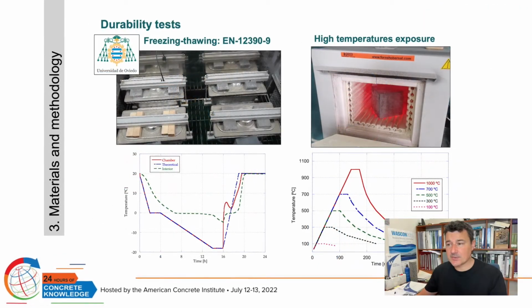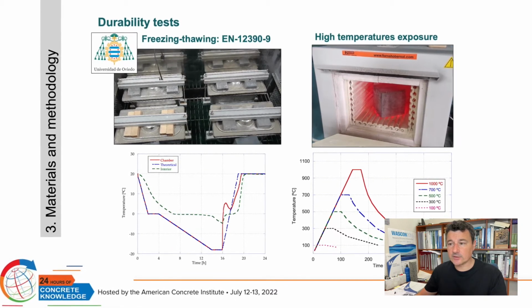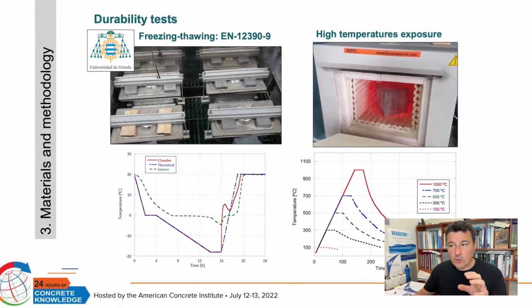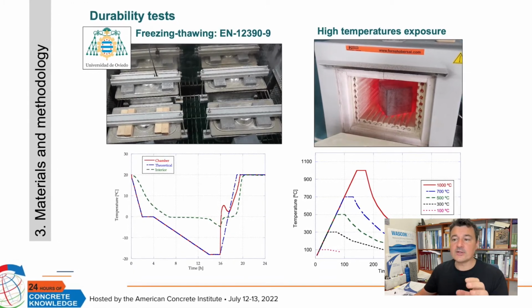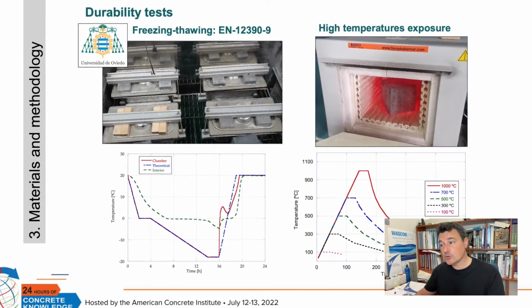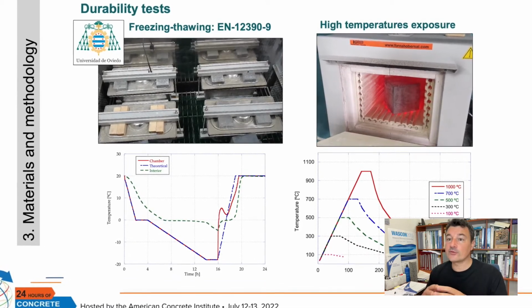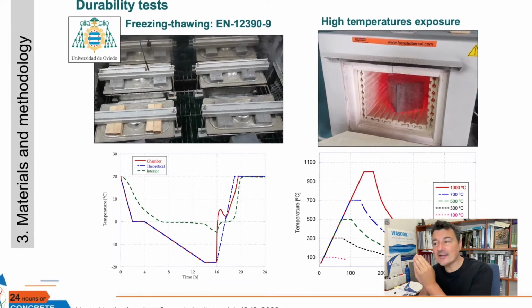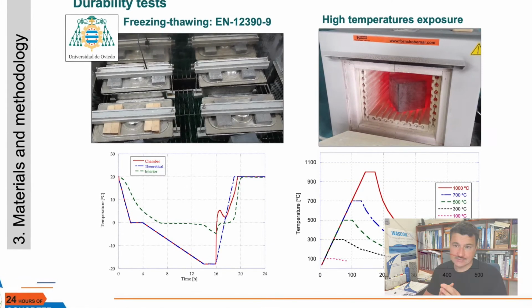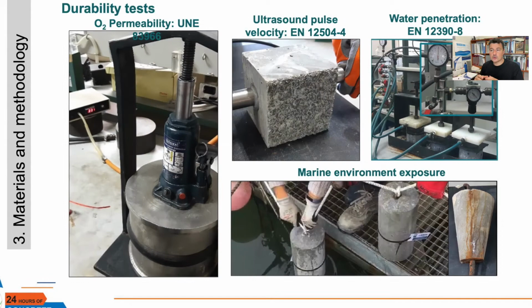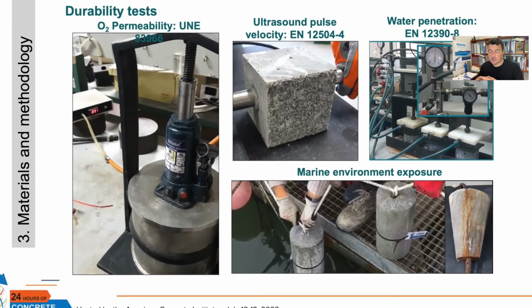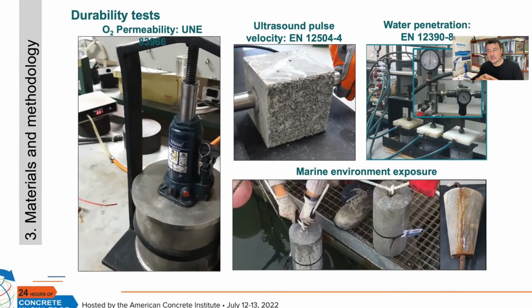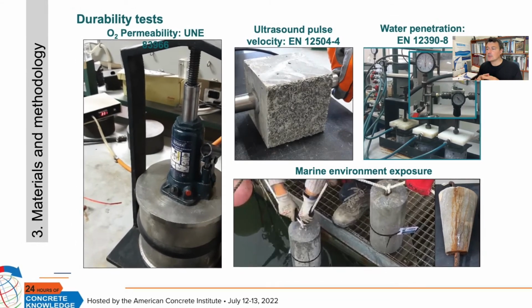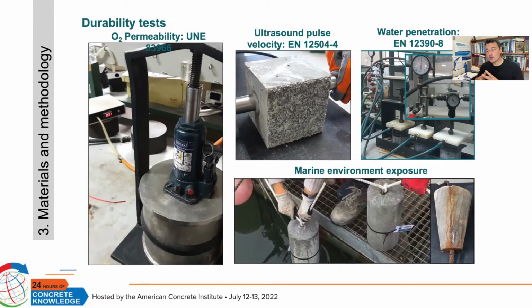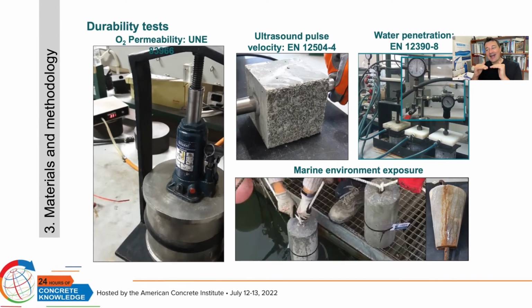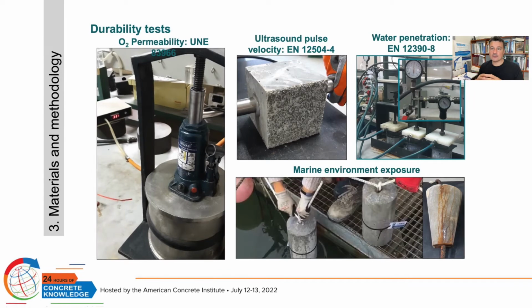Other durability tests performed on the siderurgical aggregate concrete was the freezing-thawing test performed at the University of Oviedo. Also, the behavior of the concrete exposed to high temperatures was analyzed. Also, oxygen permeability of the concrete was determined, the ultrasound pulse velocity, the water penetration inside this material, and also the material was analyzed after exposure to marine environment.